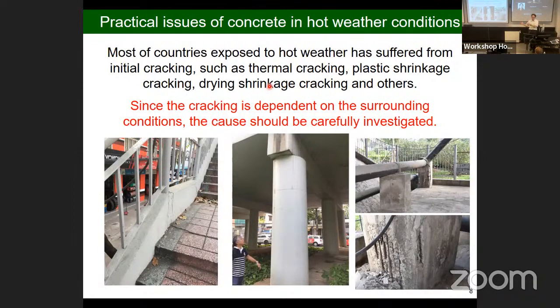Just check the potential. They also have some cement, fly ash cement, and cement blended with limestone powder. Also, the boundary condition is important. In this case, cracking happened on this side, but another side is not cracked. That is not shrinkage cracking, it is bending cracking, right?